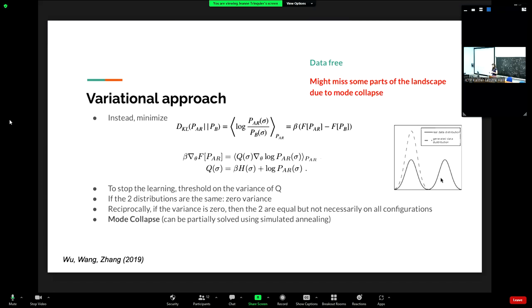This is possible because it's not hurting the Kullback-Leibler divergence: if you put zero probability on some configurations, they have a zero contribution to it. This problem is known as mode collapse. It was not the case in the maximum likelihood approach, because if you put zero probability on some regions, the divergence goes to infinity. It can be partially solved using simulated annealing, so you start at high temperature and decrease it while learning. But still, and I will show an example at the end of the talk, if you are trying to learn a very complex model, it's very likely that you will miss a lot of the landscape. So this approach is data free, but you might miss some parts of the landscape due to mode collapse.